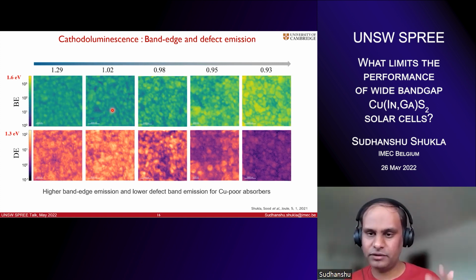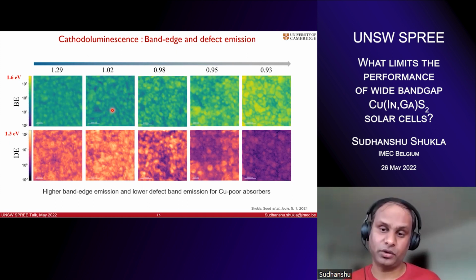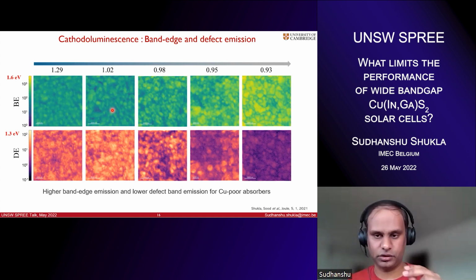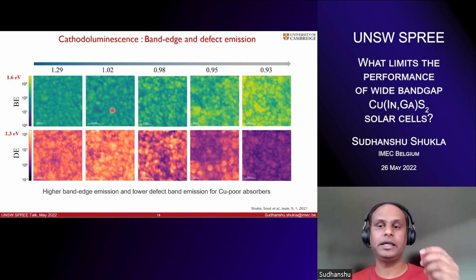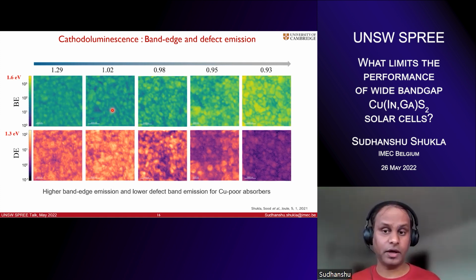I have also done a recent study on the stoichiometric absorber. If you check that study, I have shown that there are potential fluctuations going on in the stoichiometric absorber, which means you have a high degree of compensation. So at the grain boundaries, you can have high band tail recombination for stoichiometric absorbers if you have a very high compensation, which is the case for copper-poor. That study we are still finalizing, and I think very soon you will see that.